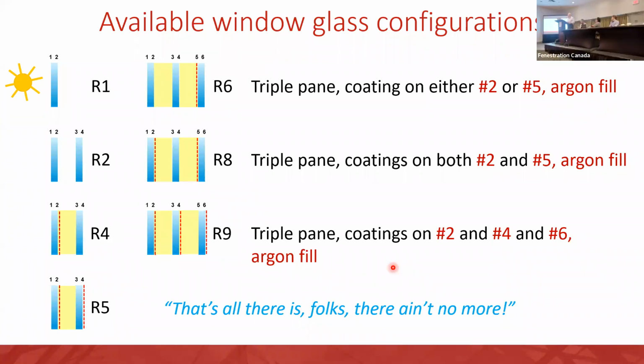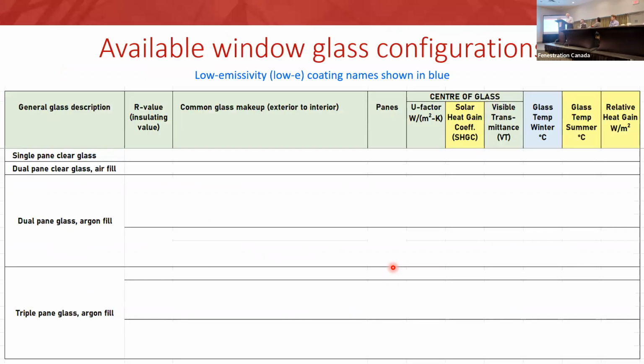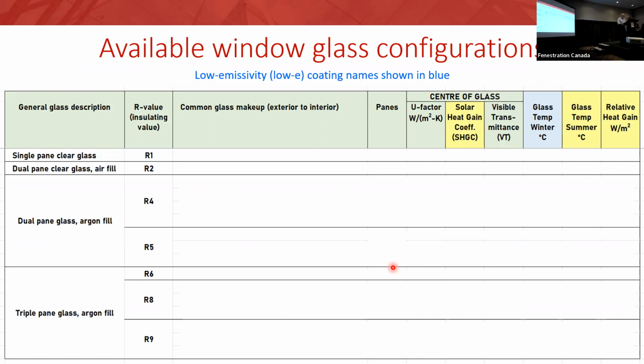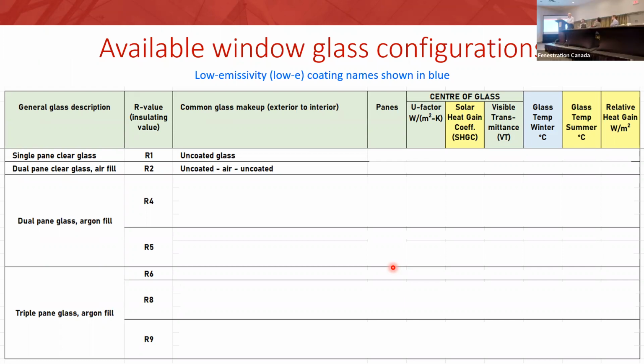And since we're not selling the R1 or the R2 option anymore, essentially there are 5 configurations that we have to work with, and we have several low-E coatings. So in my available window glass configurations table, I've ranked the data by R value, from R1 through to R9. I've also classified it by whether it's single pane or dual pane. I've included the uncoated glasses as a frame of reference, because that's the worst case scenario. In BC, we still have homes with single glazing. We still have many, many buildings with double glazed clear, and probably in other parts of Canada too. So comparing against, especially the R2 option, is relevant.